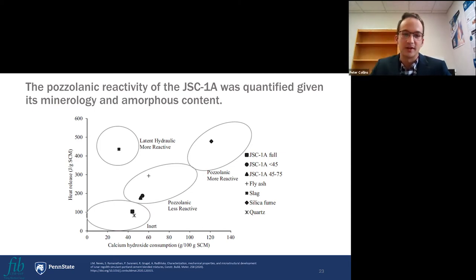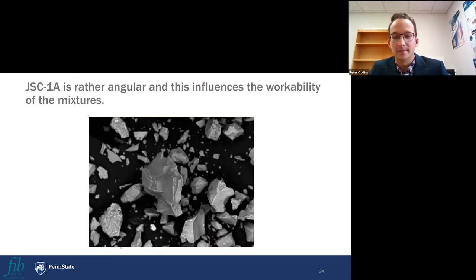But an important thing to note here is the reactivity of the finer particles as we get into the development of an in-situ lunar concrete. That plays a large role in our designs. Another important aspect of the lunar simulant JSC-1A in comparison to a fly ash is its angularity. Fly ashes are typically viewed as a ball, and so they often increase the workability, giving a ball-bearing effect where all the particles roll over one another. Whereas the angularity of the JSC-1A starts to reduce the workability because you get a lot of interlocking between the particles. And that's been an issue as I'm working with these initial designs for the in-situ lunar concrete.